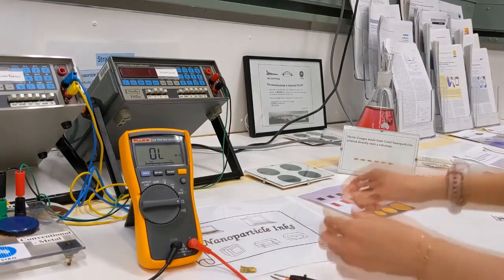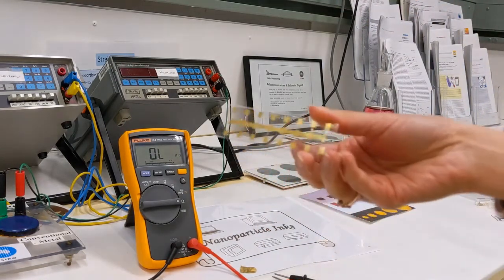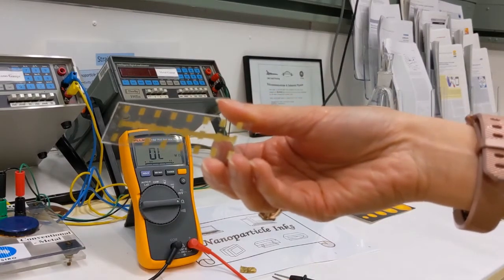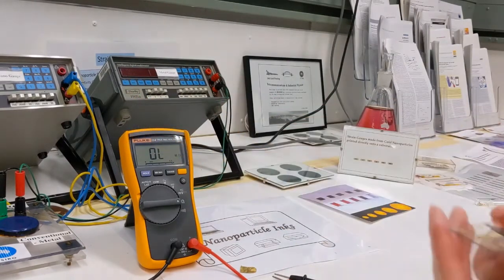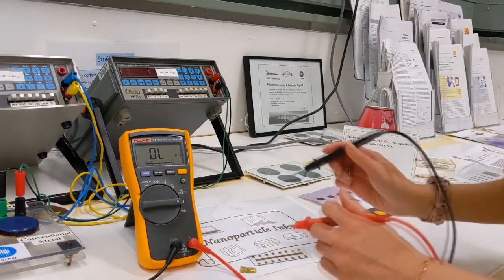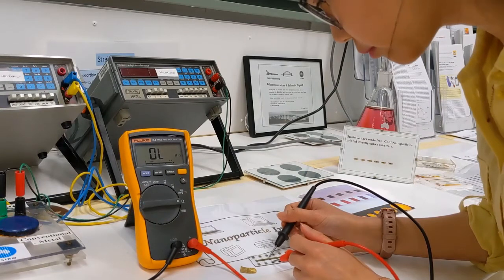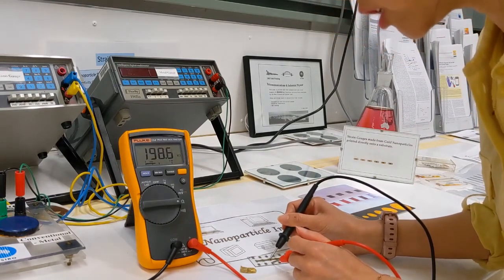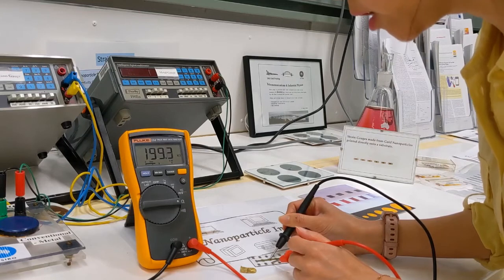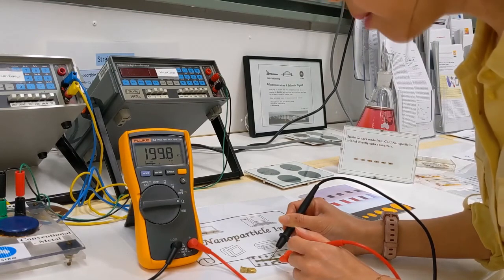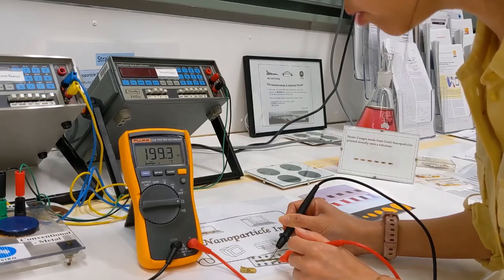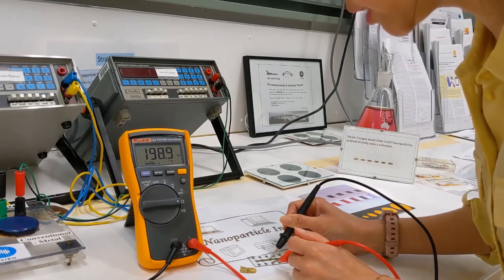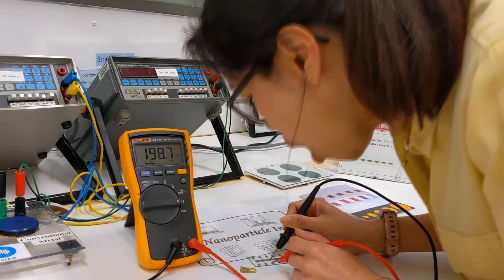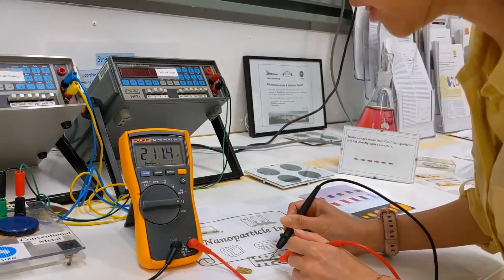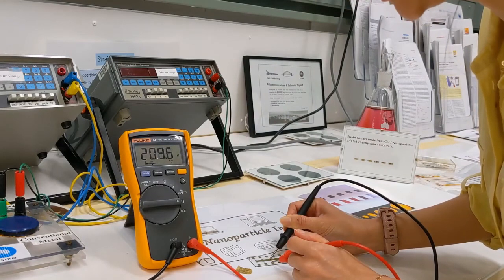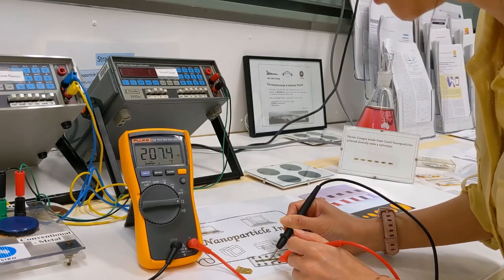Now, if I were to take a gold nanoparticle film, and these are gold nanoparticles deposited onto a glass slide, and if I were to do the same and measure the electrical resistance, you'll see that it shows quite high resistance, close to 200 kilo ohms. But what's really fascinating is that if I were to breathe over it, you'll see that the resistance will change dramatically. And that's because the gold nanoparticles are really sensitive to my breath. It's picking up the chemical vapors.